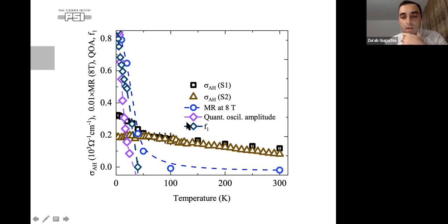Now if I plot the magnetic fraction of the static C-axis aligned structure, this sets in exactly below 25 Kelvin at low temperatures. And then we have the two temperature scales. So this is a magnetic crossover temperature, below which we get the static, quasi-static patches. So it seems that, while we have the actual magnetic ordering above room temperature, the slow magnetic fluctuations, which would be at the rate of megahertz, are detrimental for these topological properties, and you only get all the features as soon as you get a really true static C-axis aligned structure.